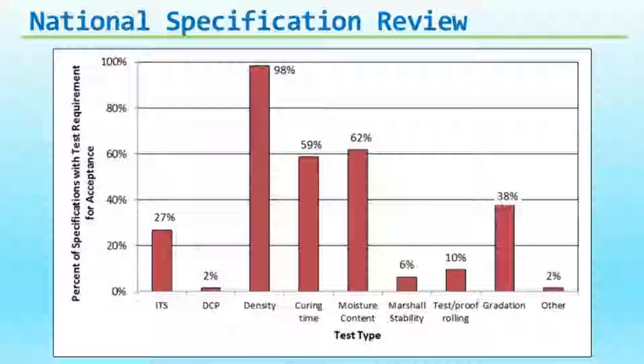Some guys were basing it purely on a time basis: 4 hours you can open it, 7 days you can pave it. Some guys were saying drop to 50% moisture content before you pave it. But a huge variety of information out there. This is just a snapshot of the different acceptance tests. You can see the middle three high bars there: density, curing, and moisture content. That was kind of what was driving it.